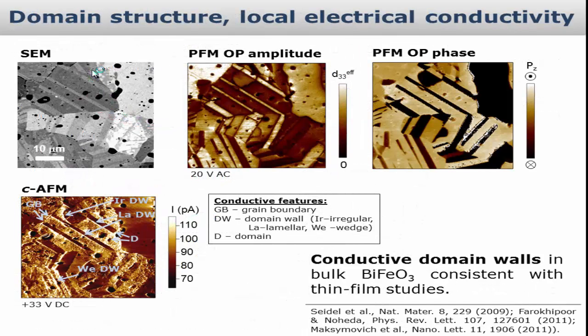So, as a possibility, we check whether there is a coupling of domain wall motion and conductivity, for example, through having domain walls that are themselves conductive. We try to check this by a combination of SEM, PFM, and AFM analysis. So this is the BiFeO sample, the main structures. We have these large regular domains. We also measured local conductivity to see if the domain walls are really conductive.